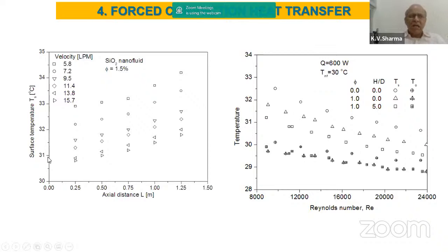So a 2 degrees centigrade decrease in temperature can be obtained as you increase the liquid flow rate from 5.8 to 15.7. This is with a concentration of SiO2 nanofluid of 1.5. So this is another way; outlet temperature has also been plotted. So ultimately, I would like to say that by the use of nanofluids, you will be able to decrease the wall temperature significantly, whatever may be the flow rate, when compared to that of the base liquids such as water.